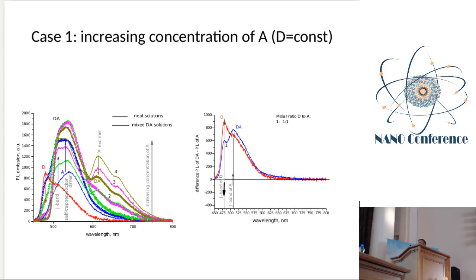And what we can do here is subtract the emission of the neat acceptor species from the spectrum of the mixed solution, and if the contribution of the components is simply additive, we should get, in principle, a photoluminescence spectrum of the donor independent of the concentration of the acceptor. But if something happens in the solution, then the spectrum of the donor will of course be changed. And this is illustrated here.